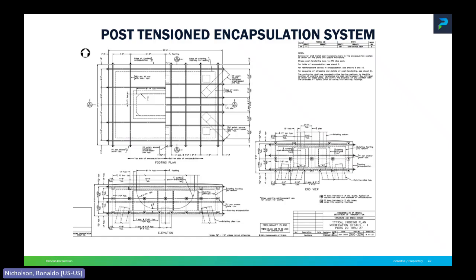Here is just a snapshot of the post-tensioning layout and design, where we see in the elevation views how they are arrayed to provide the compressive forces to basically stop the progression and expansion of the ASR. Again, it was our conclusions that the chemical reaction and mechanism would always be there for ASR, but through research, if we can apply some 5 megapascals of counteracting pressure, we can stop the expansion progression. And Dr. Sanchez basically developed his models based on that, and that went into our post-tensioning strengths and needs in the final design.